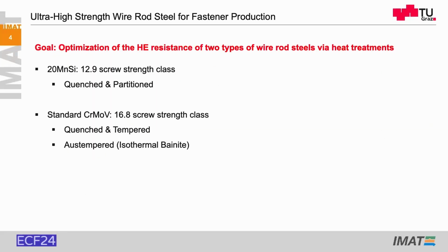Here again our two steels. 20 manganese silicon is quite nice. It's a quite cheap alloy and can be used for a so-called quench and partition heat treatment. And the second one is quite a common one, chromium, molybdenum, vanadium. The goal here was to reach the strength class of 16.8 via these two different heat treatments.